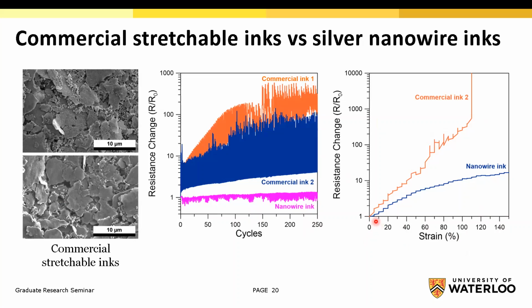increasing the strain with 5% increments up to 150%, and we observed the resistance change. Since commercial 2 performed better, we used commercial 2 here. You can see at 110%, commercial ink 2 has a resistance change much more than 10,000 times and lost conductivity, while our silver nanowire ink can tolerate up to 150% strain with only 16 times resistance change. It's a really low resistance change at this high strain value.